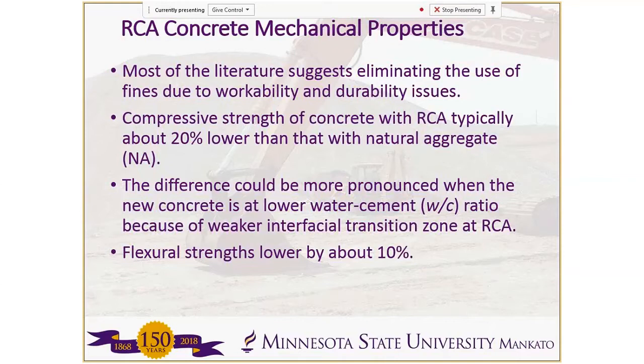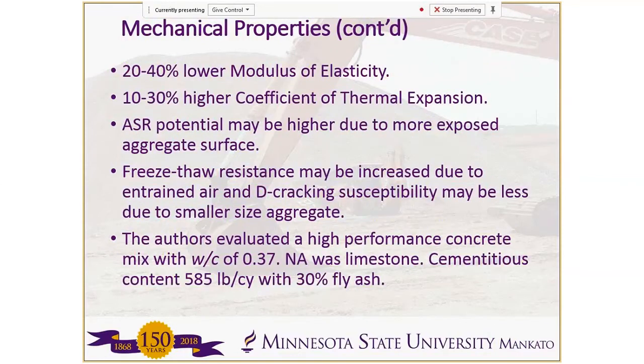Because, Bernard mentioned the interfacial transition zone earlier on, the aggregate already has a weaker interfacial transition zone than the new concrete. So this could lead to a bigger difference in your compressive strengths when you have lower water cement ratios. Flexural strengths have typically been reported to be about 10% lower. Modulus of elasticity of the concrete is about 20 to 40% lower, and coefficient of thermal expansion is about 10 to 30% higher with the recycled concrete.